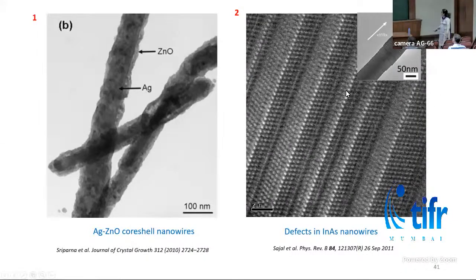This is an example of an indium arsenide nanowire. This is the low mag image of the indium arsenide nanowire, and here we can see some gray and dark contrast. When we magnify this portion, this is the bright field lattice image of the same sample. Here we can see that these are nothing but defects. So these wires had twinned defects which were periodic in nature.